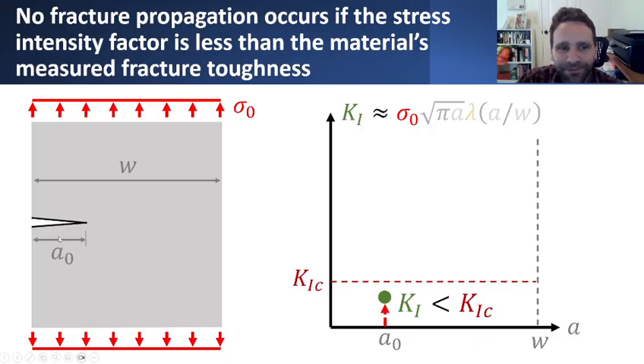Okay. So in general, before fracture occurs, and assuming that we start out with the plate totally unloaded with an initial crack size of A naught, what we'll find is we can try to start loading up this plate. We can take sigma naught and start from a value of zero and slowly increase it to larger and larger values. And what that will look like in this diagram that plots crack size on the x-axis versus stress intensity factor K1 on the vertical axis, what we'll find is that as the crack size stays the same, it's not growing at this point, we find that the stress intensity factor will continue to increase as we increase the amount of load that we're applying. So sigma naught is increasing, but crack size is staying fixed, so the crack is not growing.